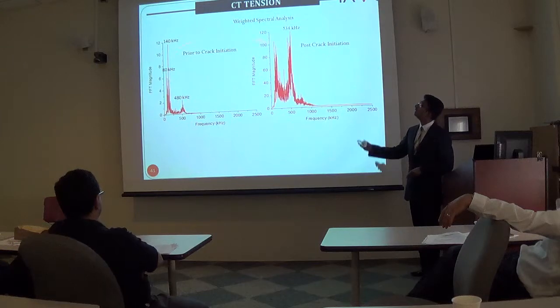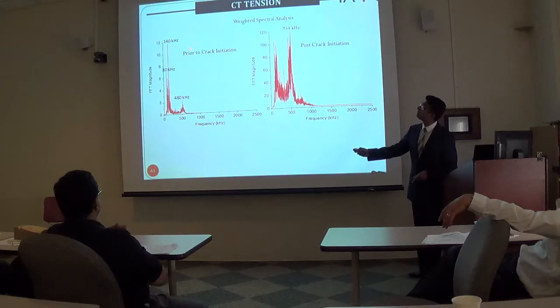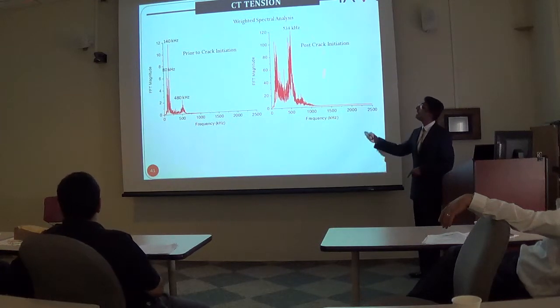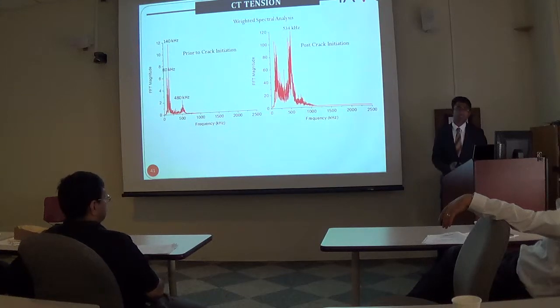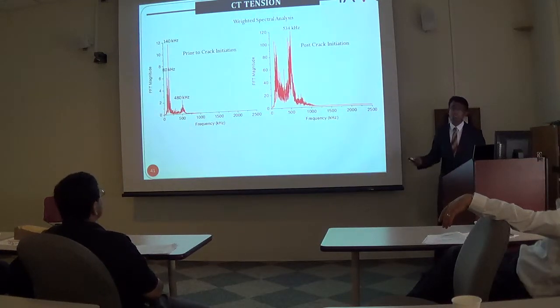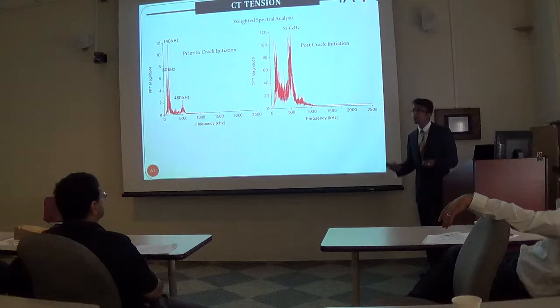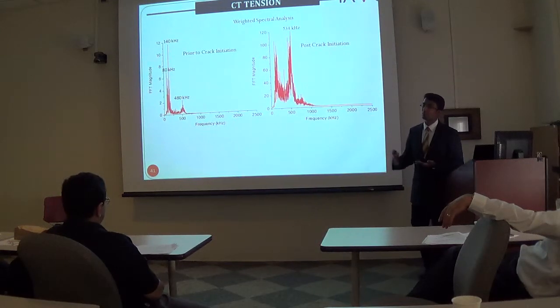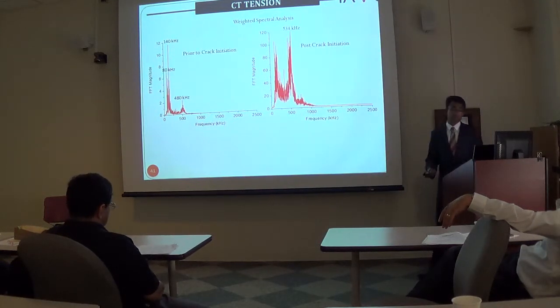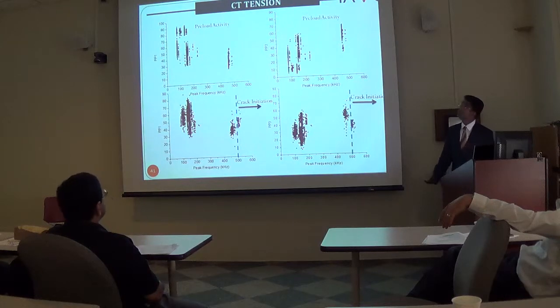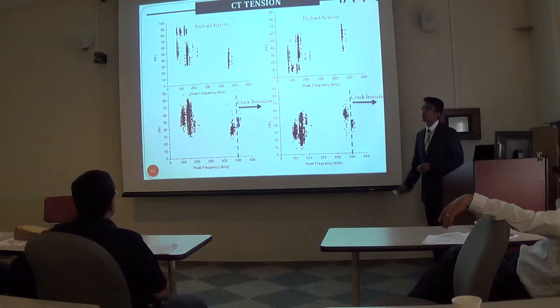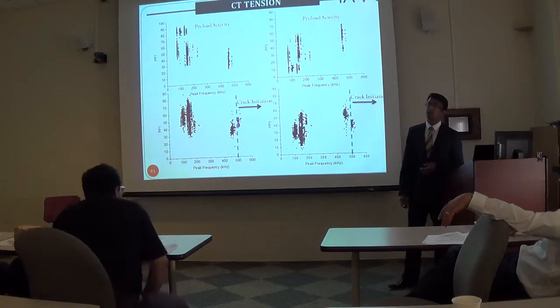So you can clearly see with this weighted spectral analysis, there's a shift in the low frequency signals to our high frequency signals upon crack initiation in the material. So this actually forms the basis of confirming that frequency-based analysis does provide an indication of the particular failure mechanism in the material. Now, additionally, partial power analysis was also utilized to confirm the crack initiation in the